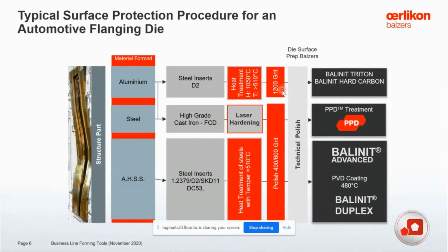Here we do the surface preparation with a variety of polishings, which includes technical polishing. Depending upon the material formed, like aluminium, we have surface solutions which can be BALINIT Triton or BALINIT hard carbon. For steels, dies for skin parts sometimes also get laser hardening, and we have pulse plasma diffusion treatment for big tools. For advanced high strength steels, we have BALINIT Advanced or BALINIT Duplex solutions, which are usually done by physical vapor deposition coatings, and these coating processes are applied at a process temperature of 480 degrees centigrade.